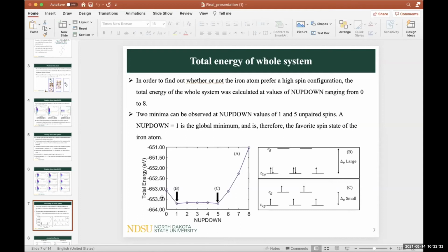Okay. So in the case of low spin configuration here, I would expect that the local magnetic moment would be somewhere closer to 1. In the case of high spin configuration, I would expect that the value would be 4 point something. Normally it would be lower than the maximum value. So it's a good exercise to look at the OUTCAR file and double check it. Okay, I will double check it. Thank you. More questions to Sarah?